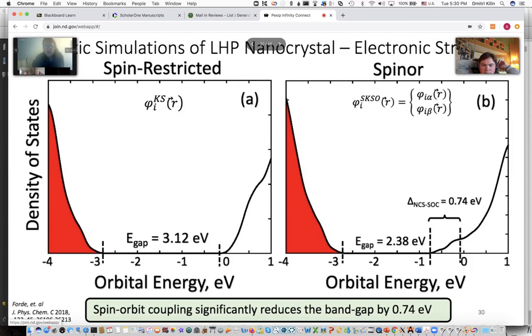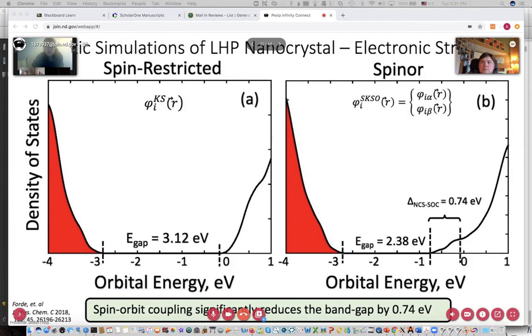eV. And if you compare the density of states for the conduction band, there are major quantitative and qualitative differences. So here it decays and flattens out for the spin restricted, but for spin orbit, you have some electronic states which are spread out further, which create subgaps in the conduction band, which will be important when I talk about the non-radiative relaxation. Next slide.